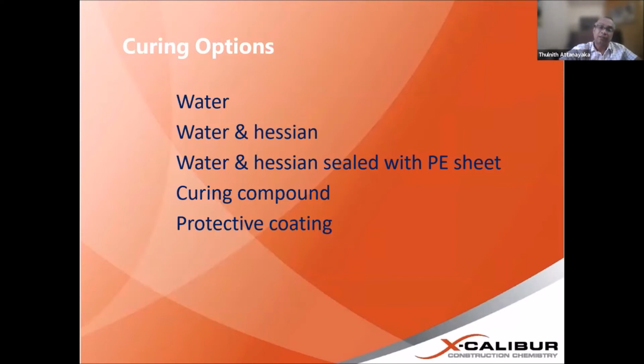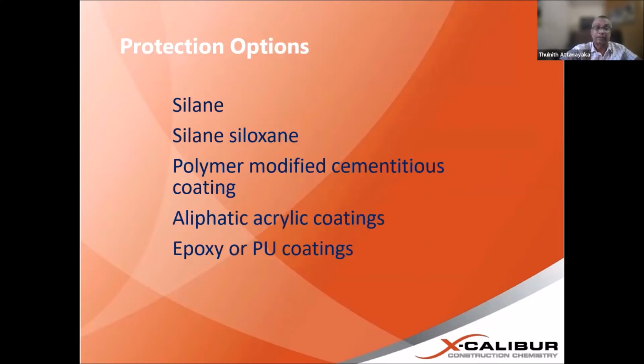Let's say we have to do a high-end and more critical repair with concrete and reinforced concrete. Of course, if access is not there, for the working platform and scaffoldings you invest huge costs. So to protect the repair, you have to use some kind of high-end coatings rather than only protective coatings for the curing, because it will give two aspects: curing plus durability protection. We can use silane, siloxane, and polymer modified cementitious coatings like the 2K waterproofing. Those are the protective coatings we need for concrete repairs.